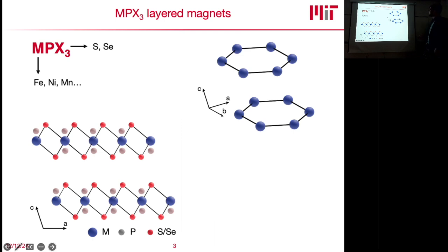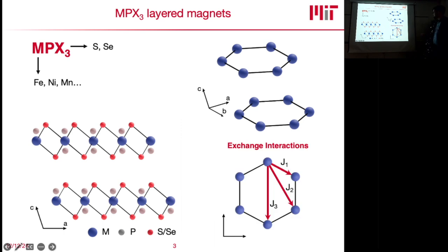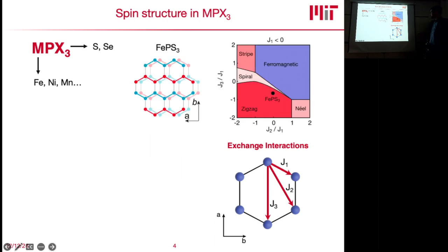will turn out into different types of magnetic configurations. Because the choice of this ion will control the different exchange interactions in the material, so first nearest neighbor, second nearest neighbor, and third nearest neighbor interaction, and also the interlayer coupling between these materials. And so, depending on this, we can actually realize a plethora of different magnetic states. And so the material that I want to focus on today is iron phosphorus trisulfide, which is here in the so-called zigzag phase. And so the specific choice of this ion then results in these zigzag chains here, where you have ferromagnetic chains, which are basically antiferromagnetically coupled to adjacent chains. And then again, antiferromagnetically coupled to the next layer below.